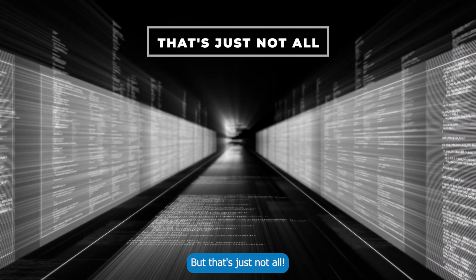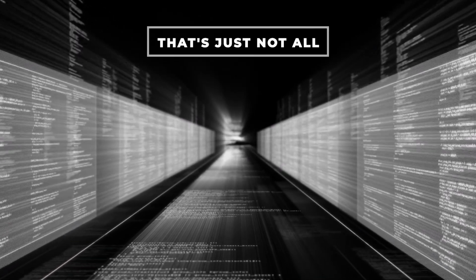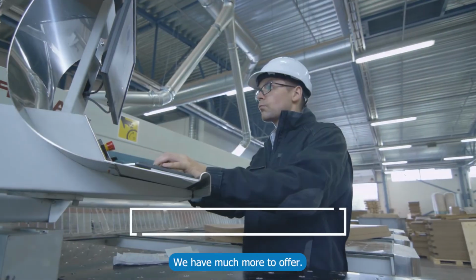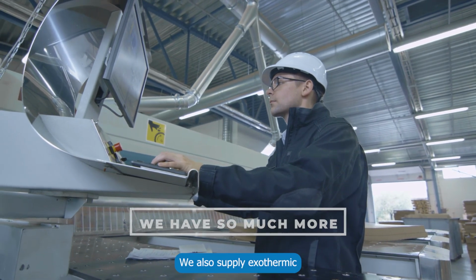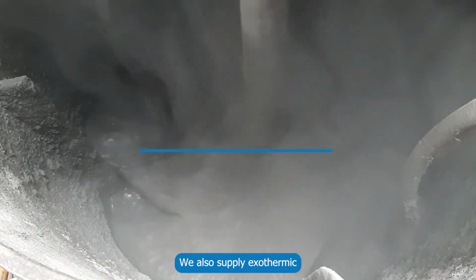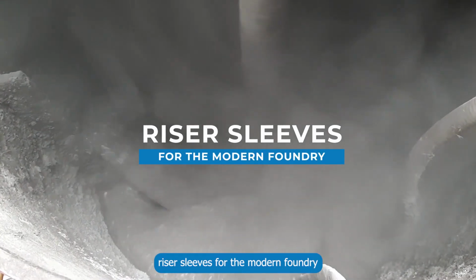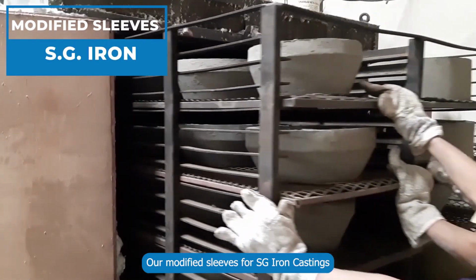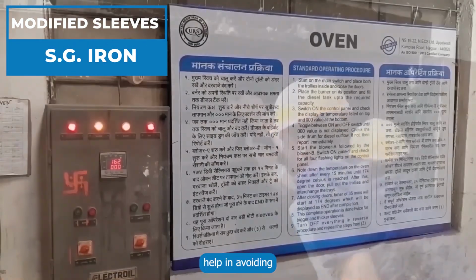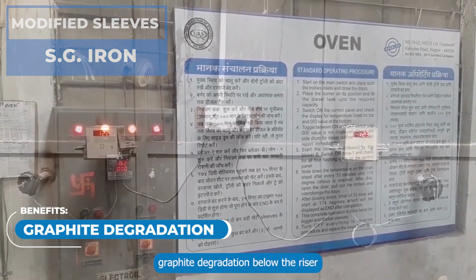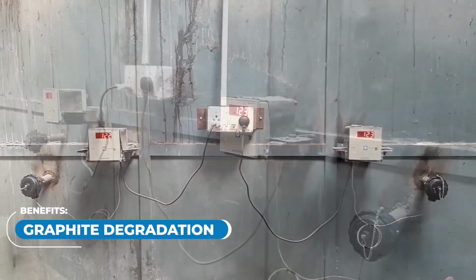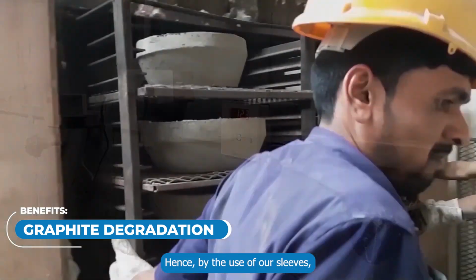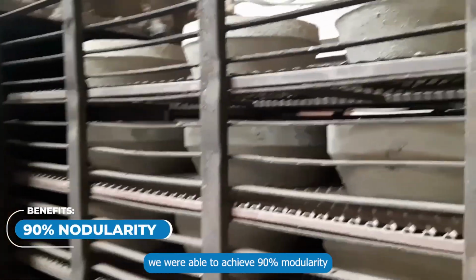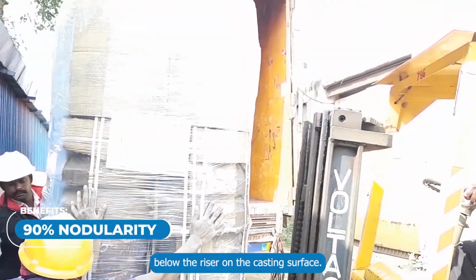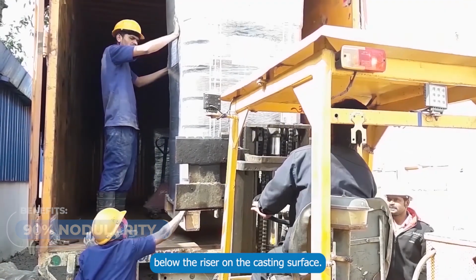But that's just not all. We have much more to offer. We also supply exothermic and insulating riser sleeves for the modern foundry. Our modified sleeves for SG iron castings help in avoiding graphite degradation below the riser. Hence, by the use of our sleeves, we were able to achieve 90% nodularity below the riser on the casting surface.